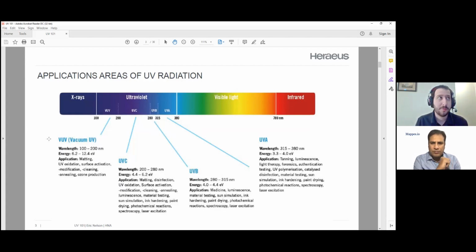You could form a plastic by a traditional thermal route where you take a hot melt of different plastics and you dry it out and it becomes a hardened structure. You could also shine a UV light onto a chemistry and initiate a chemical reaction that causes a chain reaction and causes the material to cross-link and become harder and more functional.